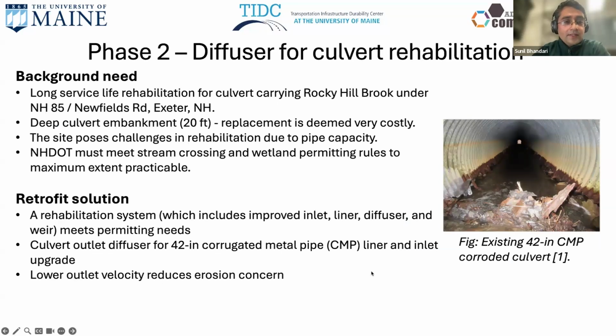For phase 2 of the project, it was a diffuser for culvert rehabilitation. It was part of a larger rehabilitation project of the culvert carrying Rocky Hill Brook under New Hampshire 85 Newfields Road, Exeter, New Hampshire. The culvert had a deep embankment of about 20 feet, so the replacement was considered very costly. The site posed challenges in rehabilitation due to pipe capacity, and just slip lining was not good enough because it reduced the capacity.